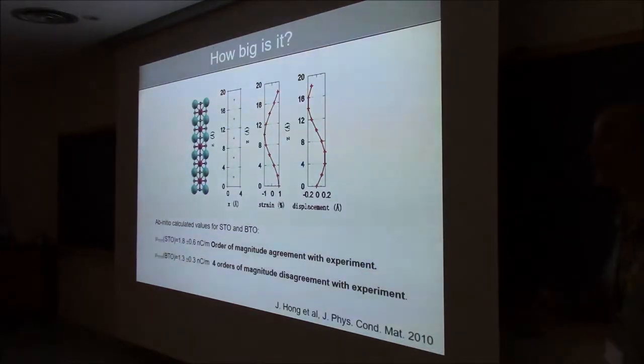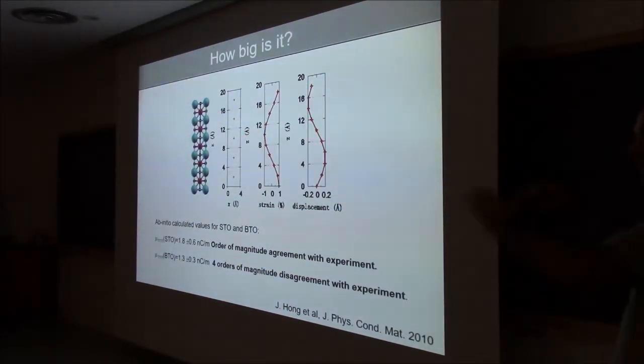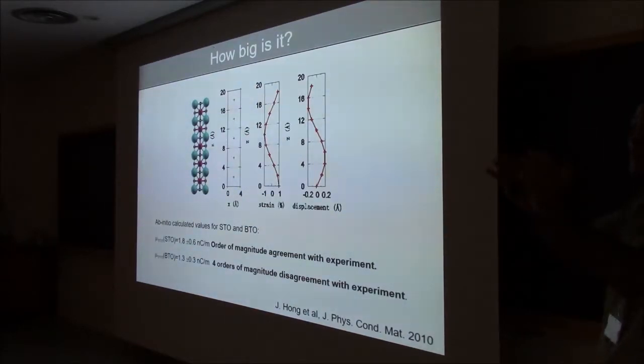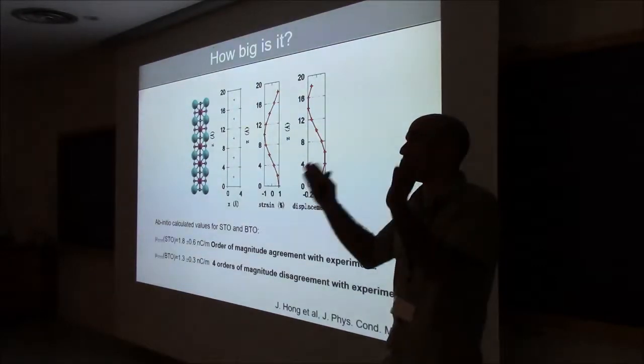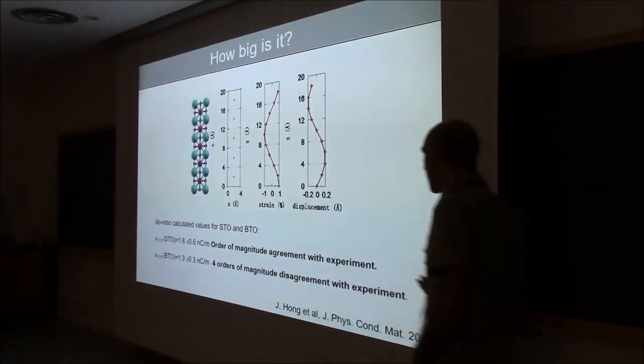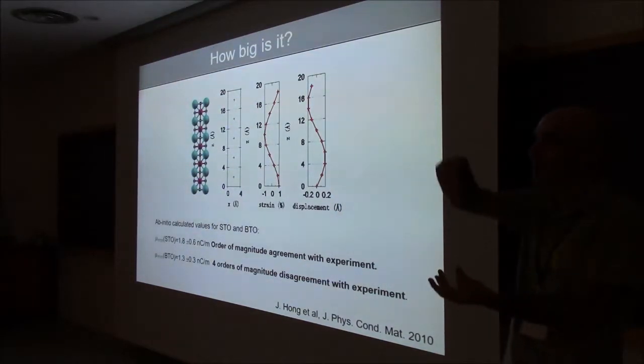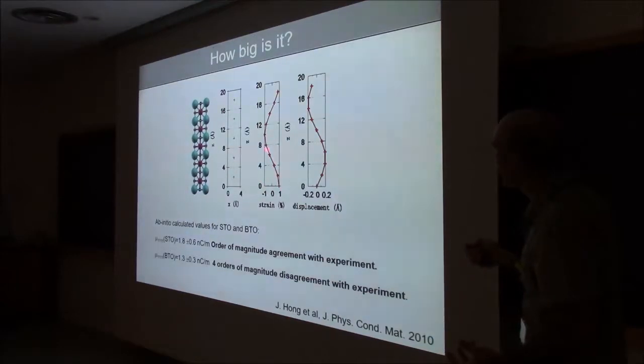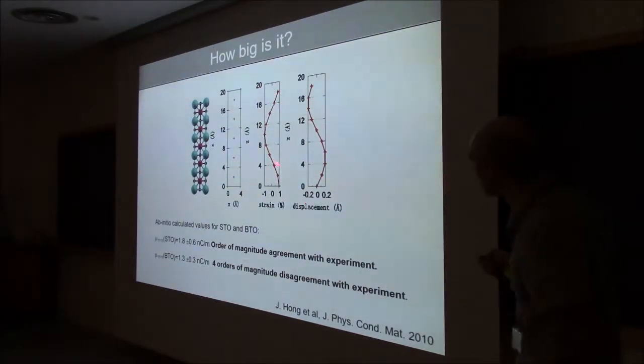And this is inherently difficult because any of you who knows anything about DFT would know that usually you assume a periodic boundary condition. You make an infinite crystal by assuming that the lattice on the left, you match it with the lattice on the right, and you can make an infinite crystal from a very small unit cell just by repeating. But of course, a strain gradient breaks the periodic boundary condition, right? If I have something compressed here and something extended there, I cannot now take this unit cell and put it here because they don't match. So our trick to do that was to do an accordion-shaped unit cell that would be, say, extended here, compressed at the bottom, and extended here again, and then match this to this, and then the two would fit. And here I have a strain gradient, and I would look at the polarization here.